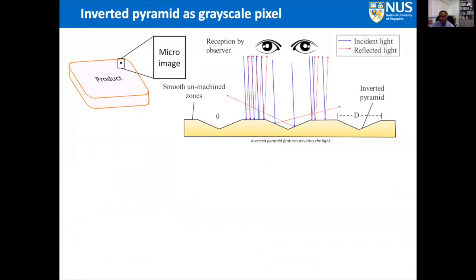Basically, grayscale digital images vary from black at the weakest intensity to white at the strongest. When a micro image is being generated on a metal surface, a concave feature can be machined to produce a different level of luminance to represent the level of darkness of each pixel. Compared to the unmachined zones without any feature, the light rays illuminating the machined concave feature are diverted to other directions instead of being reflected back to the observer. This could result in a relatively lower luminance level perceived at the concave zones.